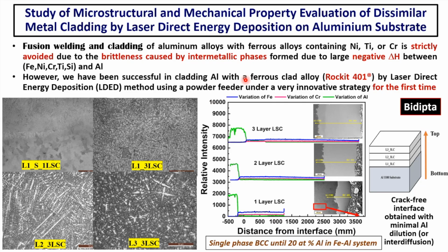So to join iron with aluminum is a nightmare. And certainly there are different approaches using a buffer layer or a preventive layer or various other approaches. Generally, users would avoid fusion, and go for cold welding or extrusion or friction stir welding kind of approaches. So Bidipta has been able to show that you actually can fusion weld or develop iron-based alloy clad on aluminium without incurring the penalty of producing a large volume fraction of brittle phases and making the interface brittle. And the approach for that is actually very clever.